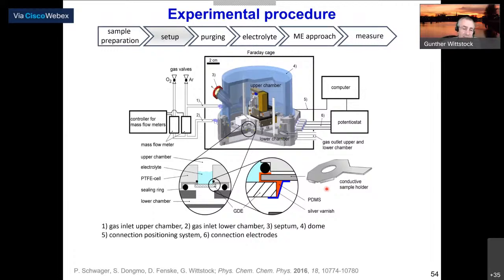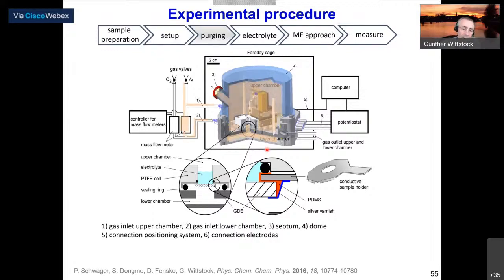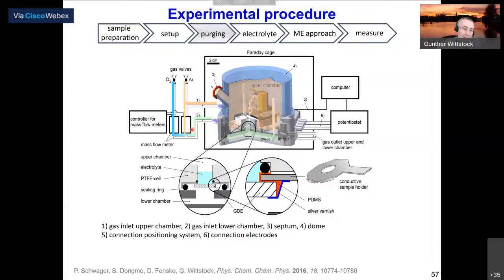I don't want to go into these technical details, but at the end, an oxygen partial pressure from here will cause a diffusion through the gas diffusion membrane into the atmosphere, which is argon above the sample, and then carried away with that. So we would have constantly a passive permeation of oxygen into that cell. We start by filling both chambers with argon. Then we inject our electrolyte solution into that argon atmosphere. Then we start again, and now we start the upper chamber with argon and the lower chamber with an argon-oxygen mixture.